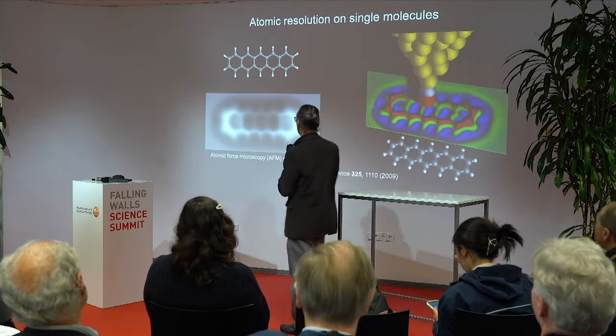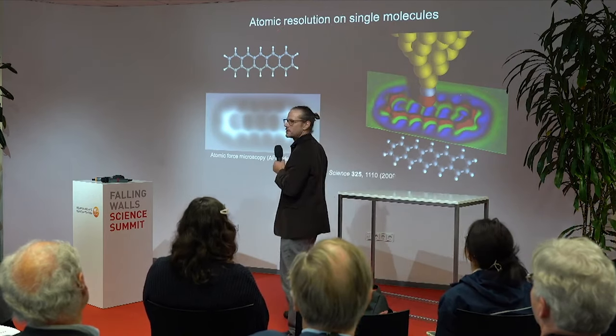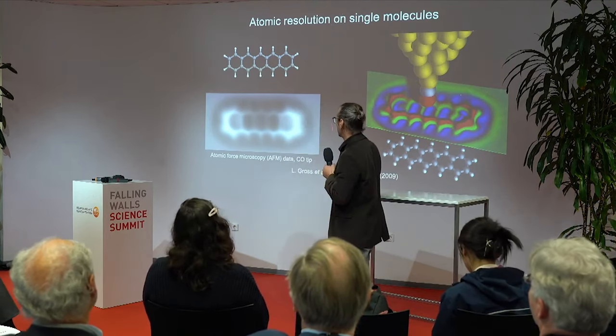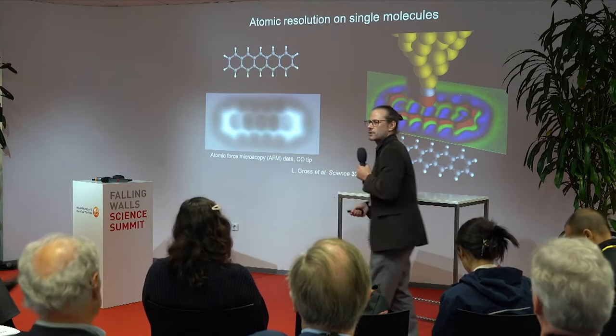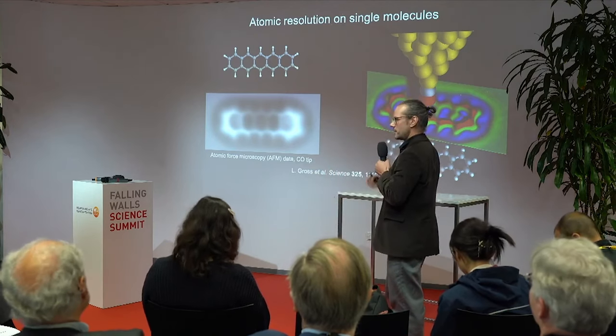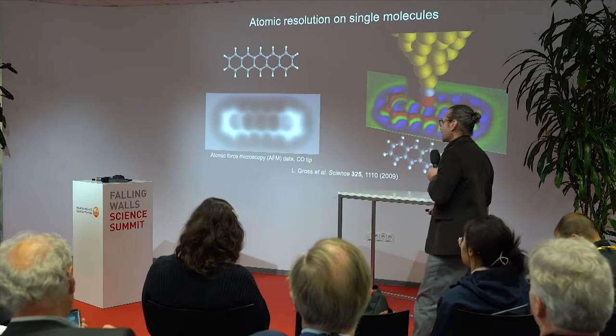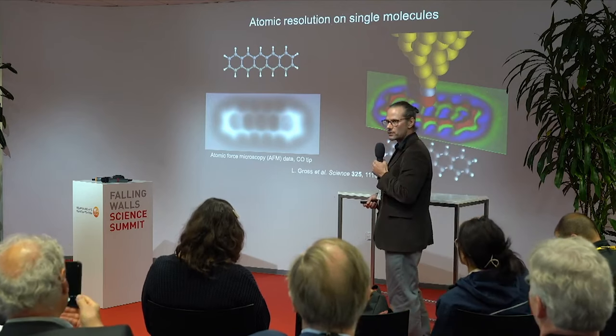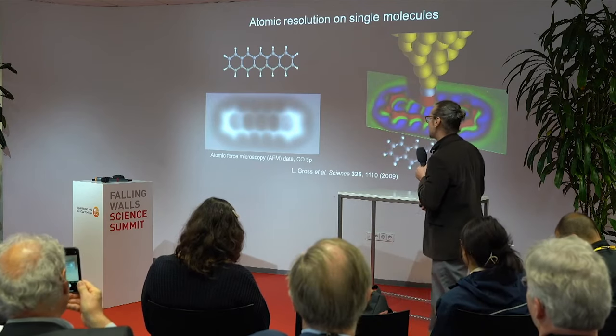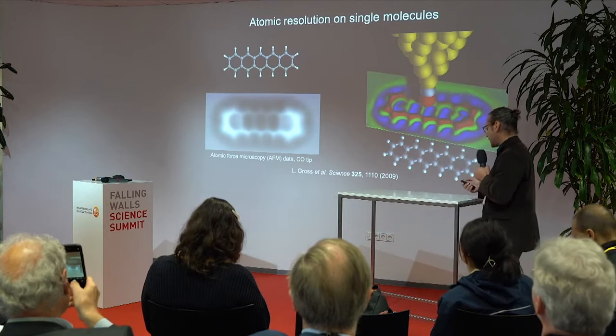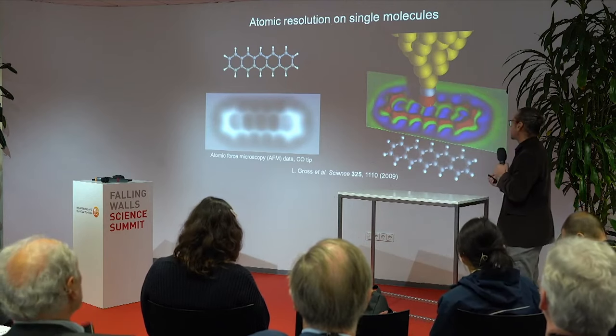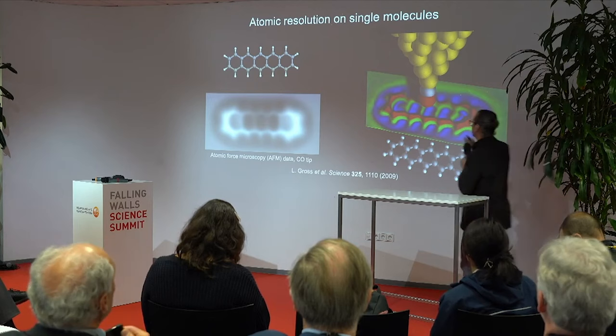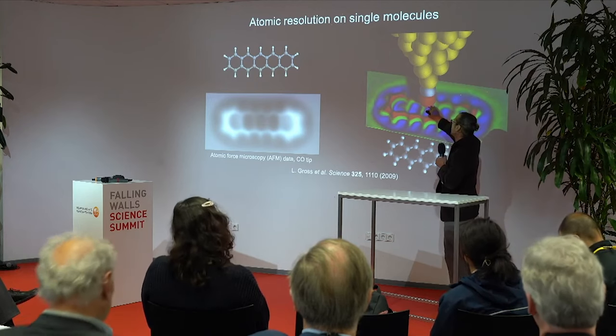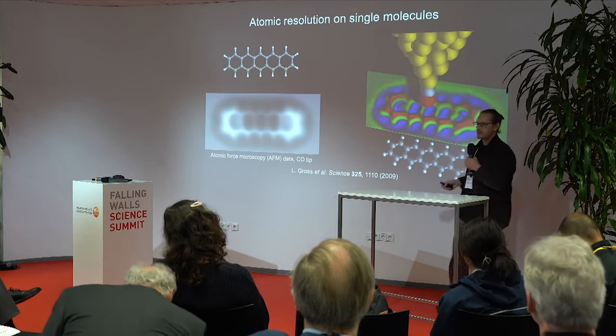So you all know these chemistry textbook models. This is pentacene. And this is an atomic force microscopy image that we take of such a molecule that is adsorbed on a surface. We do this with an atomic force microscope. And there's one particular trick that we play and that we found gives us high resolution: we attach a single carbon monoxide molecule to the end of the tip. So this is an oxygen, this is a carbon. The metal tip is behind.